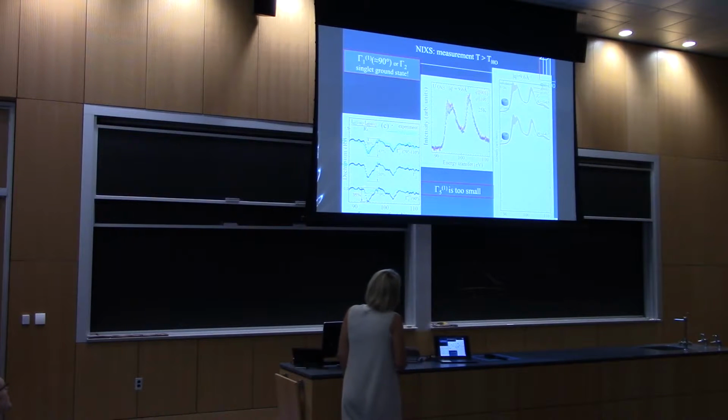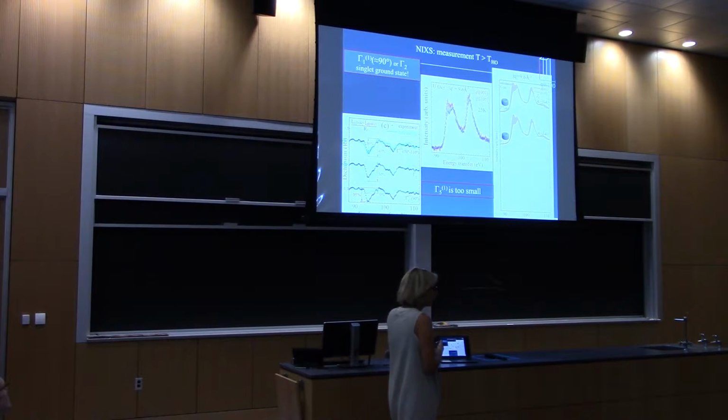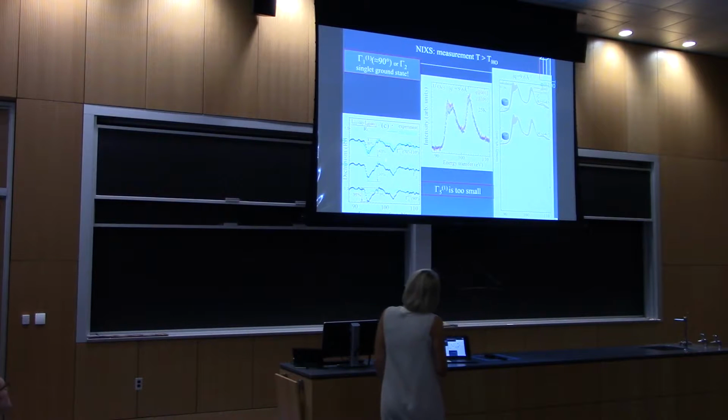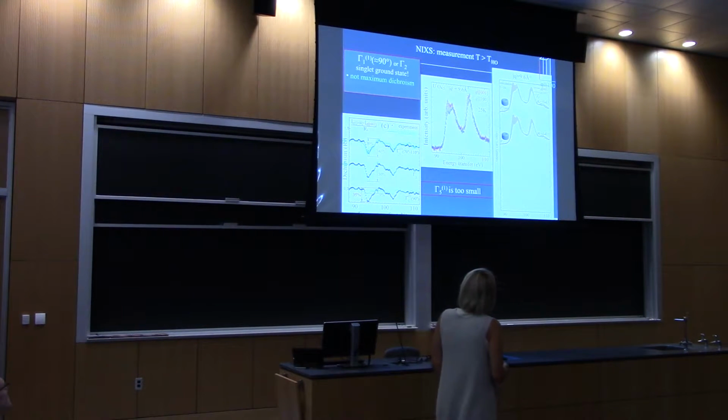But also here we have to say the gamma 2, well, the simulation gives us a dichroism which is somewhat larger than the measured one. In the gamma 1, we can mix in, of course, some of the JZ0. We could make the dichroism somewhat smaller. I would like to leave it like this. For the time being, I can say we do not observe the maximum possible dichroism. We have a big dichroism, well described with the gamma 1, relatively well described with the gamma 2, but there is maybe some dichroism. It would have been bigger than what we actually observed.